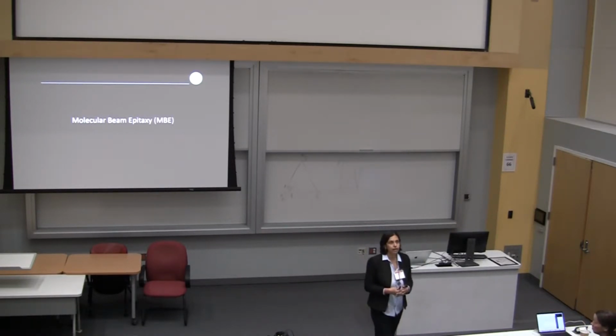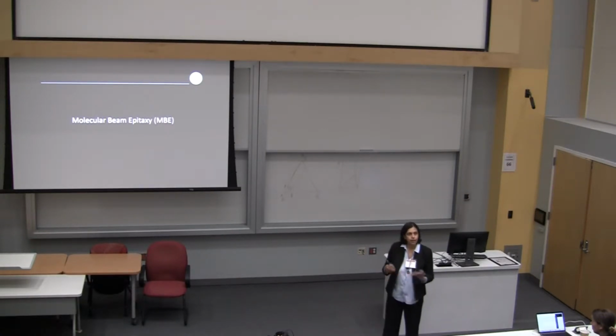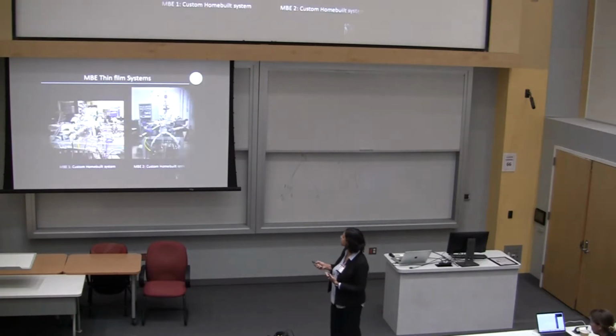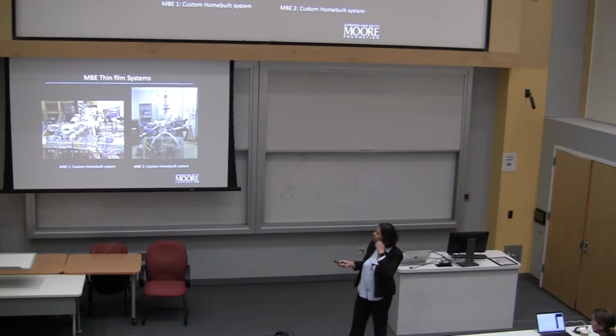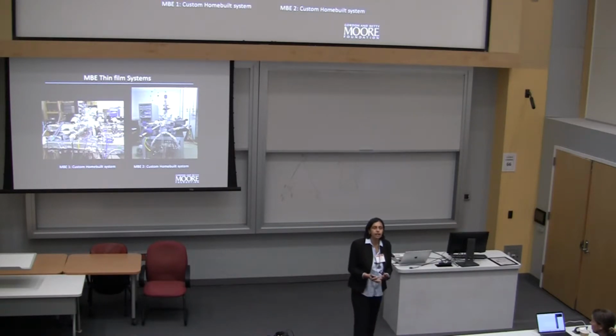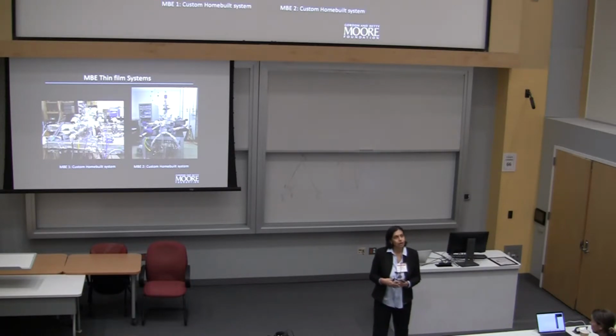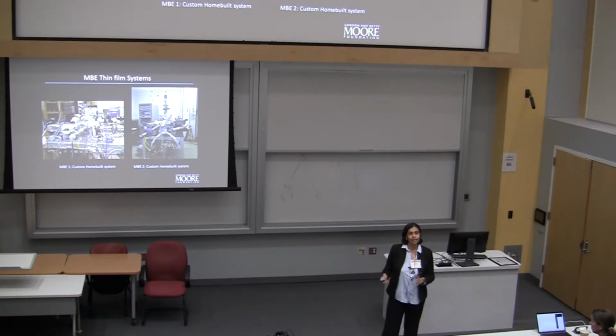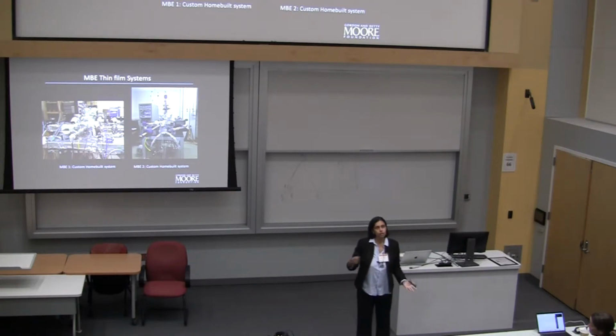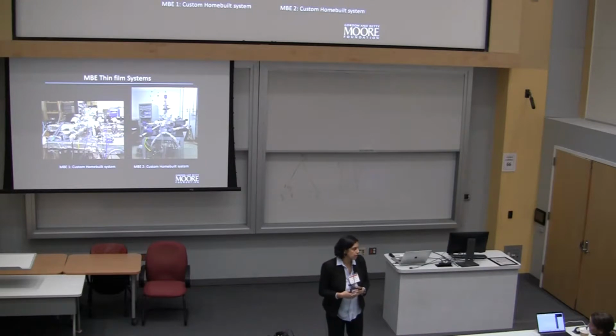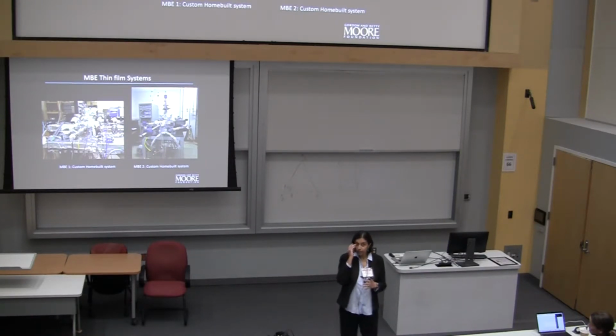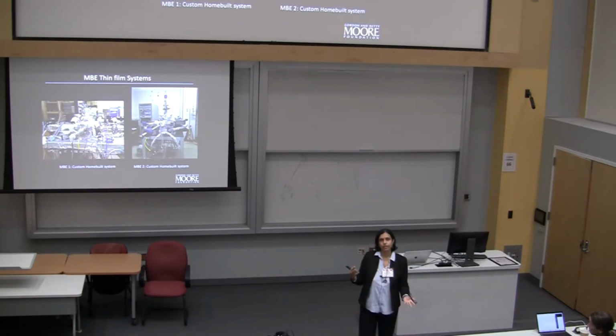Now I want to move on to talking very briefly about MBE. So MBE, as you know, is a powerful tool to grow thin films. We actually have 2 MBE systems in our lab, and you can see from the way they look, they're both home built. Now you might have seen commercial gigantic oxide MBE systems. The nice thing about chalcogenide MBEs is that they don't have to look like that. They can be small vacuum chambers hiding under this aluminum foil, and the walls don't have to be water cooled. You can basically build your own MBE for about $250,000. A large fraction of the money goes into the RHEED, which is about $35,000 to $40,000, and then most of the rest actually goes into purchasing the evaporators. So an MBE doesn't have to cost $1 million.